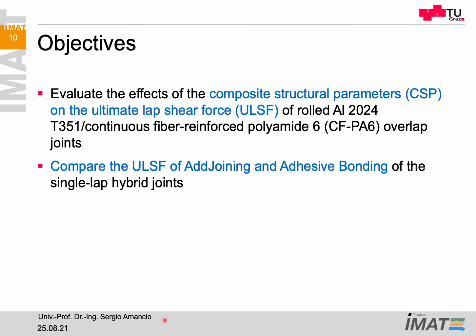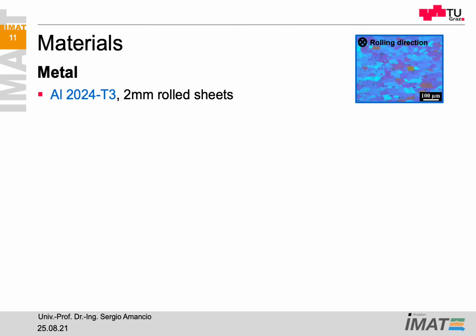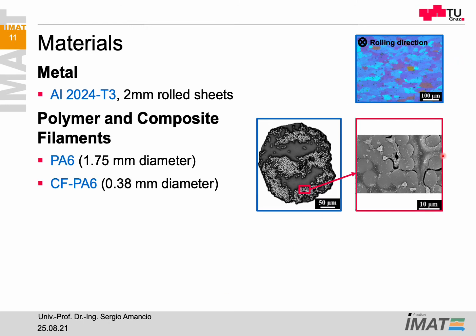And to compare the ultimate lap shear force of the AddJoining in comparison to adhesive bonding reference joints. For that, as I mentioned, we select aluminum 2024 2mm rolled sheets with this microstructure, as you can see here on the top. And we work with two filaments, one unreinforced polyamide 6 and the continuous fiber reinforced polyamide 6, as you can see here in the picture, a cross section of the part of the filament.